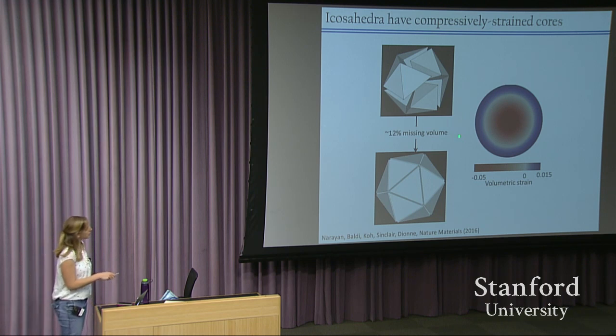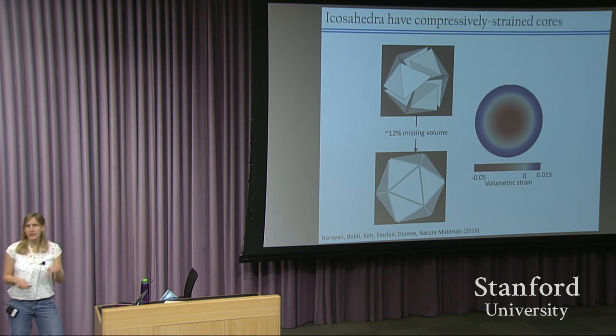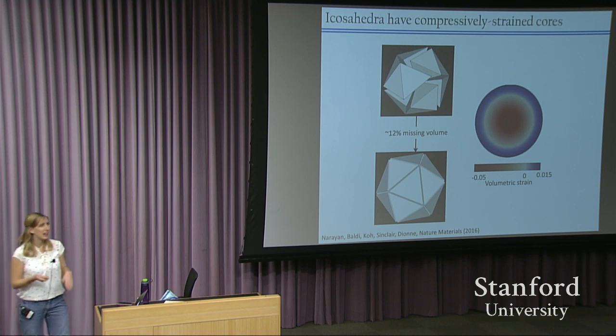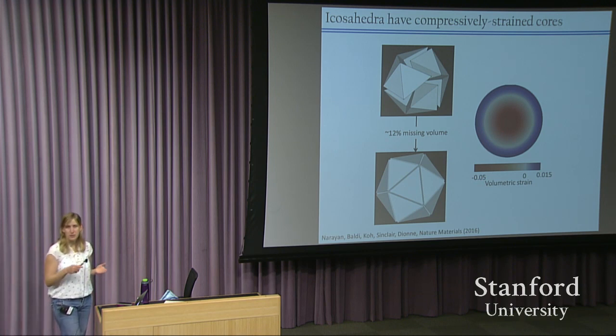So this compressive strain at the core makes it really hard for hydrogen to get in there, regardless of how tensely strained the shell is. It's going to be very challenging for hydrogen to make its way into the core. And that's why we think we're seeing coexistence of phases in the icosahedra.